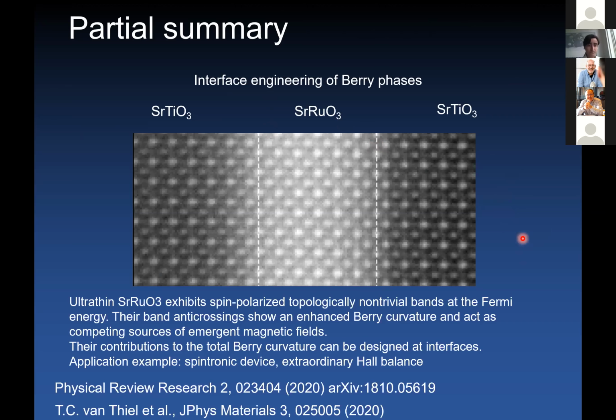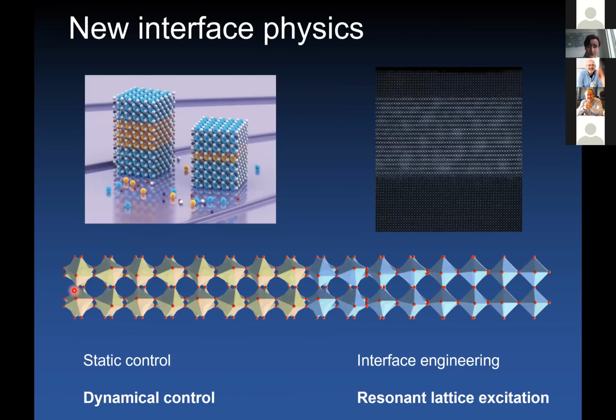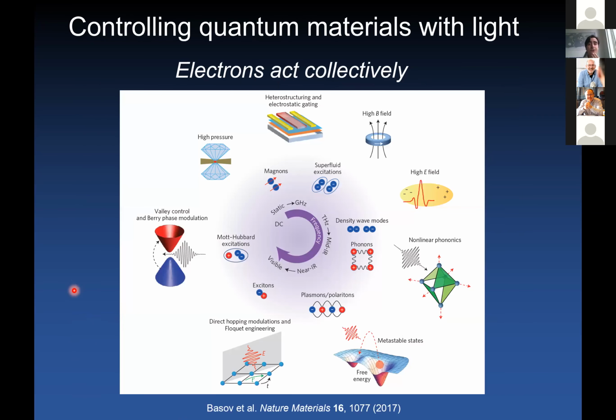Okay. So just to wrap up this part, I showed you that when you thin down strontium ruthenate, the system starts to exhibit spin polarized topologically non-trivial bands that show anti-crossings in momentum space and sources of Berry curvature. And this can be manipulated at interfaces, and you can use this to realize spintronic devices. Now, in the last part of my talk, I would like to mention a little bit the possibility of dynamical control of the electronic properties of oxides.